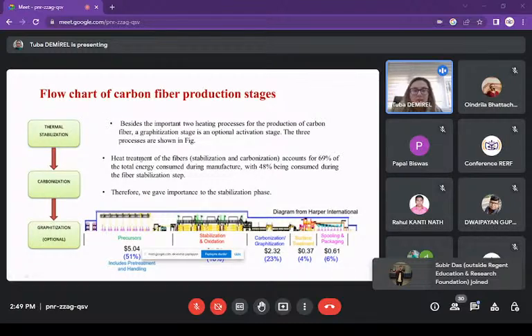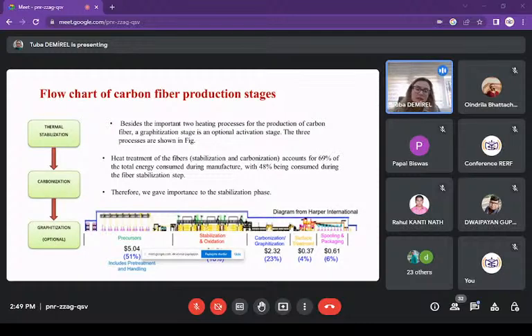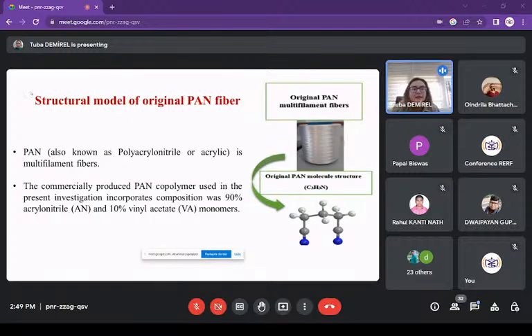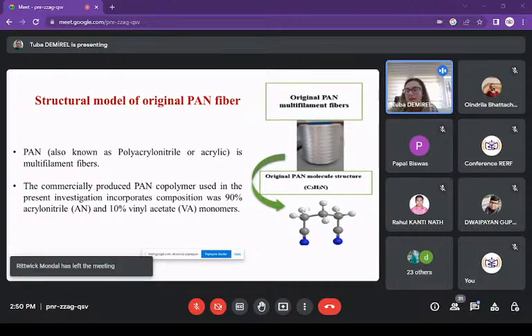Then heat treatment of fibers accounts for 69% of the total energy consumed during manufacture, with 48% being consumed during the fiber stabilization step, and we give importance to the stabilization phase. And this structure model is the original PAN fiber. On the right, the picture shows PAN fibers, which are white in color, and this is the original PAN molecular structure.